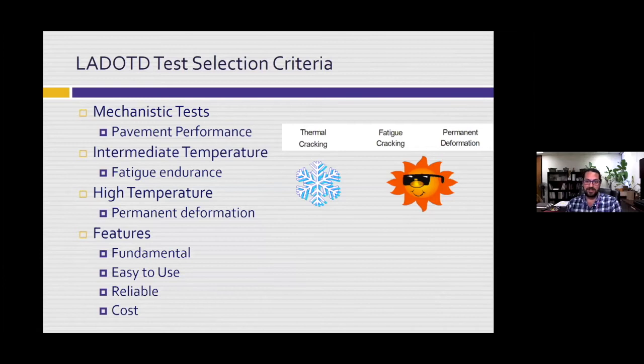Particularly in Louisiana, we were interested in intermediate temperature cracking to give us fatigue endurance. We do not have a lot of thermal cracking here in Louisiana, so it's not a very large concern. And even our fatigue cracking is on the higher temperature end of the fatigue cracking spectrum. At high temperature, of course, we are concerned with permanent deformation, but again, with our conventional mixtures over the last several years, permanent deformation has not been an issue. So the features we were looking for: something fundamental, something easy to use, something reliable and repeatable, and something that is not going to drive the cost up. If we're going to rely on our contractors who conduct our mixture designs to run these tests, it can't require a $250,000 piece of equipment.